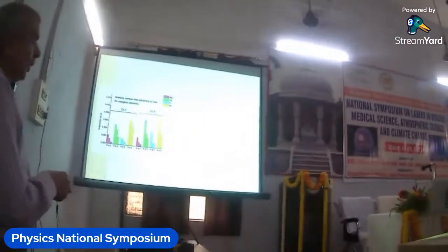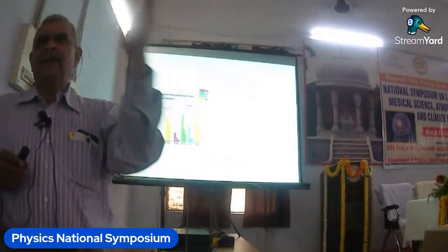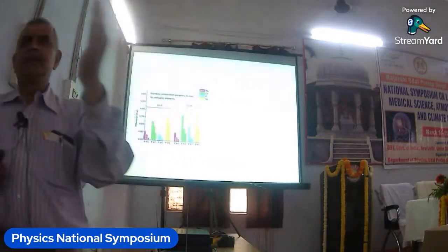We have analyzed many gallstones, but here I am showing the result of two gallstones. And a similar figure is observed in gallstone B. So what you can conclude is that if you have a small stone, then the intensity of magnesium at the periphery is large, less in the middle, and very less at the center. That means the concentration of magnesium is decreasing.